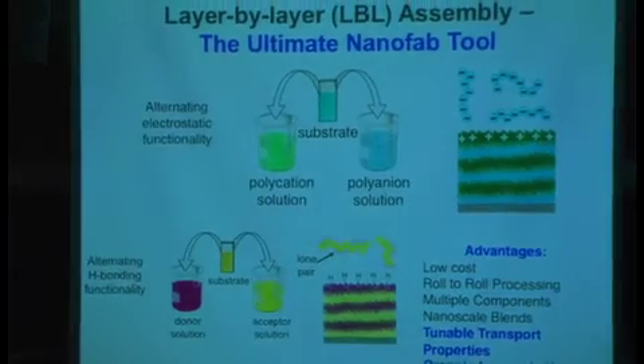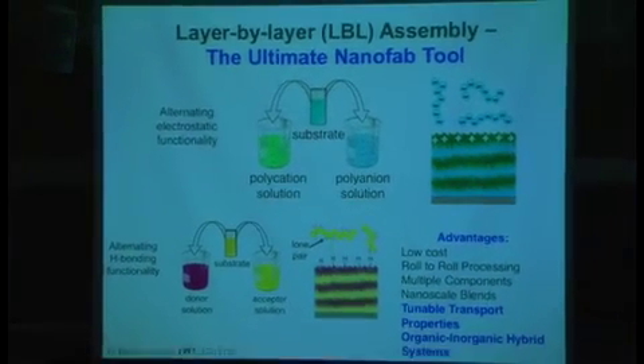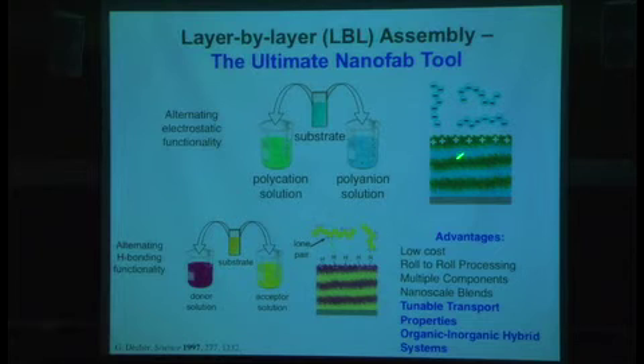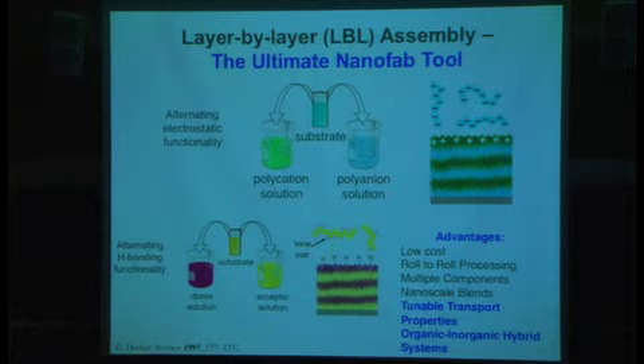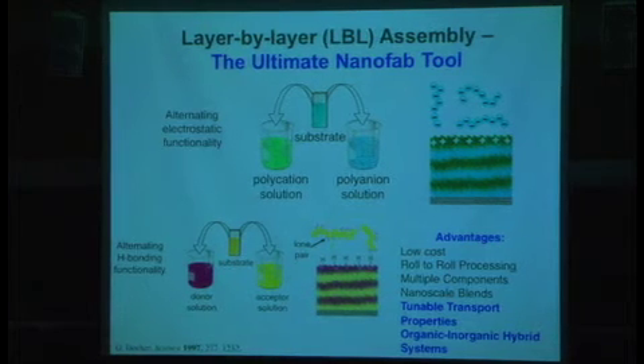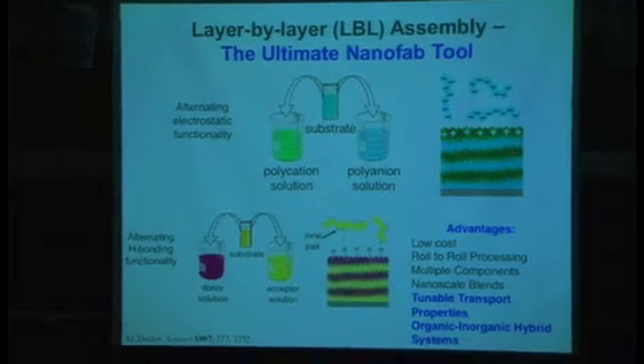Now we can adsorb a second polyelectrolyte on the substrate. It follows the same rules, and we can keep going back and forth, dipping and adsorbing. These layers tend to be anywhere from as thin as a few nanometers to as thick as tens of nanometers. And we can actually observe interpenetration of polymer chains down to about 1 to 4 layer pairs in these systems. And that was actually determined using neutron reflectivity studies, a kind of analogy of the Cheshire Cat in a way, the experiment that Ed Merrill was describing so long ago. You can also use hydrogen bond functionalities to have complementary polymer chains built on these surfaces.